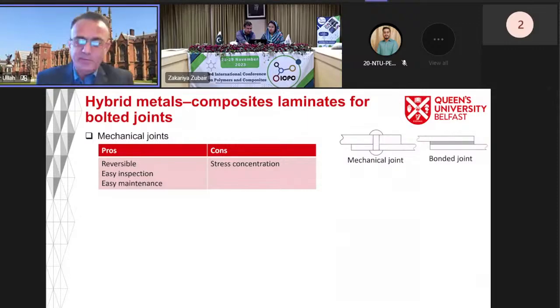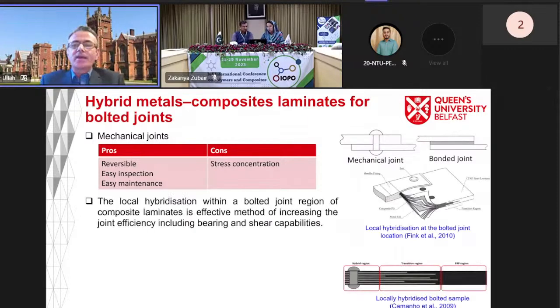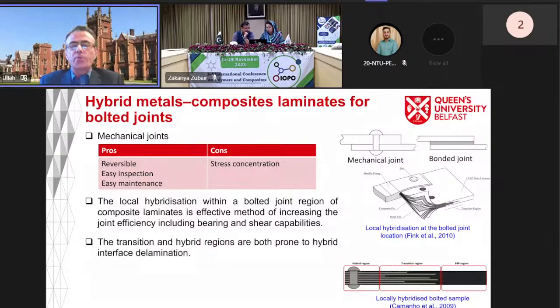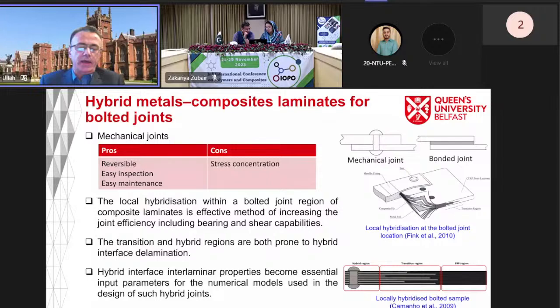Okay, sorry about it. So as you can see here, we have these 3 regions. One is the FRP, then the transition region, and then the hybrid region in these hybrid metallic composite laminates. Our main idea for this project was to find out the interface fracture toughness between the metal and the composite. In this case, we are using a modified transverse crack tension experiment to measure the mode 2 fracture toughness.